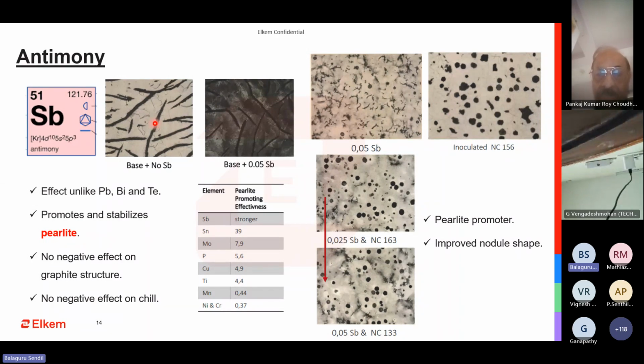When it comes to gray iron, it is a very strong pearlite promoter, with no influence on the shape and size. In case of ductile iron, of course, it can boost the nodule count. If you keep increasing it, it can increase the nodule count even at very thick regions, thick section castings, windmill, ductile iron, pipe fittings, all these areas. But the drawback is that it's a very strong pearlite promoter. So if you're trying to take casting samples from there and do tensile strength, you might end up with challenges. So this is antimony.